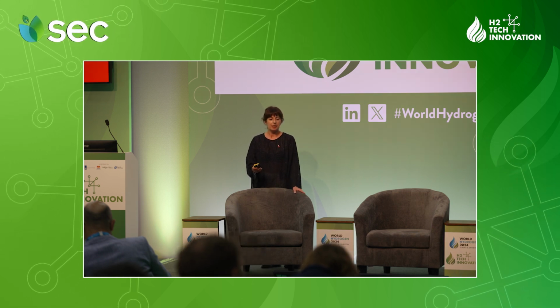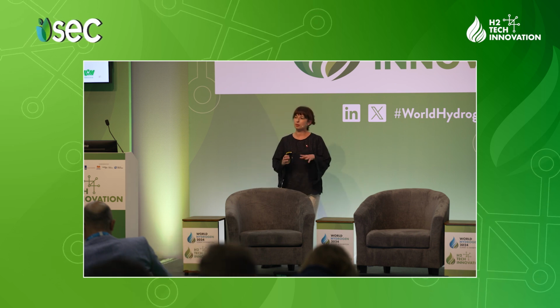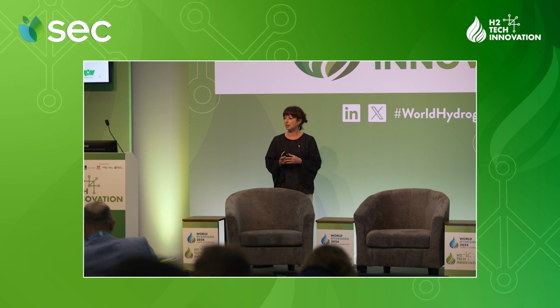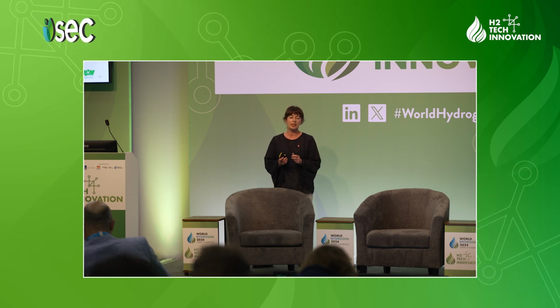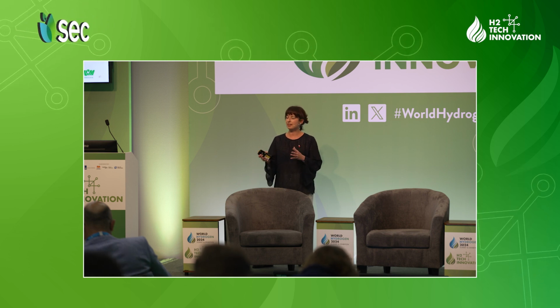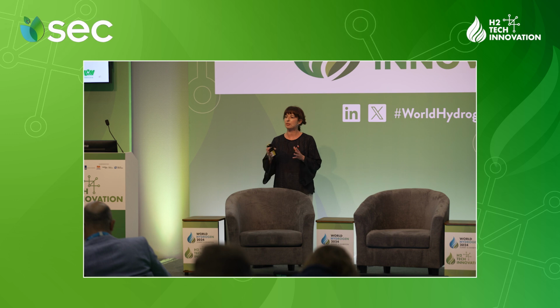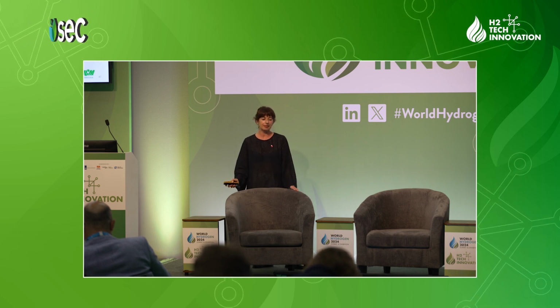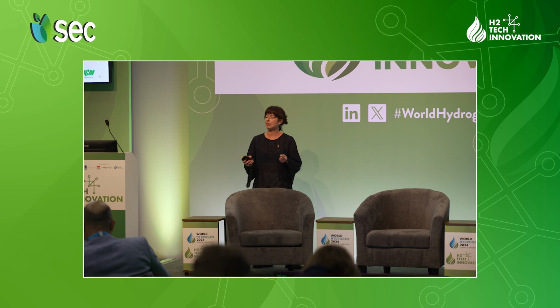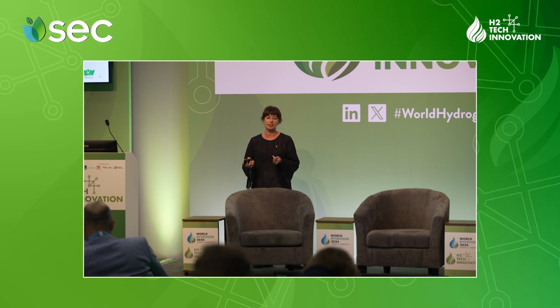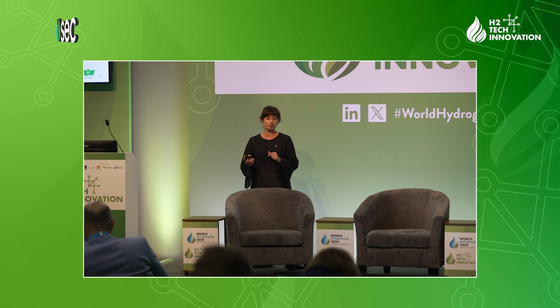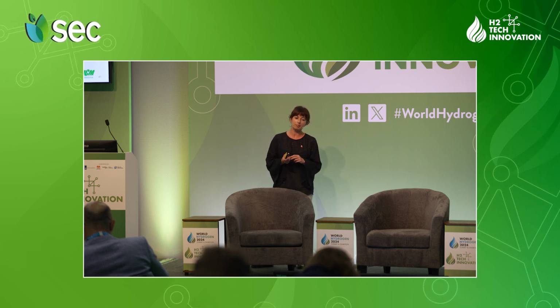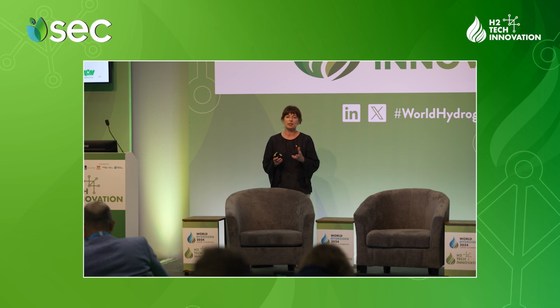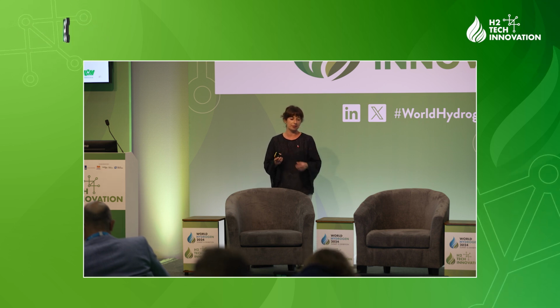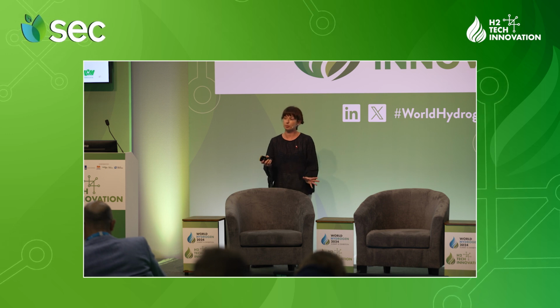In general, what we did was to evaluate for our sealing materials permeation, leakage, and RGD properties. Permeation seems to be dictated by diffusion, as solubility seems to be very low. The permeation coefficient allowed us, in accordance with theory, to rank our compounds in terms of polymer type and formulation. I didn't report the details here, but we also ran testing in parallel on helium for permeation and leakage to show that the orders of magnitude were similar for the permeation coefficients. Rapid gas decompression events seem to possibly not be an issue in the case of hydrogen for standard RGD proven materials.